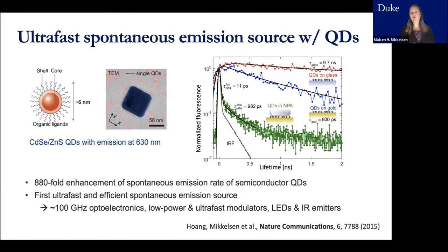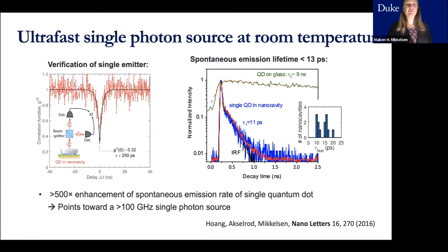This could also be very useful in enhancing II-VI emitters that can often typically be very dim. I want to point out that we're not exciting them at this point at high rates, because we start to have stability issues for the materials, that they can photobleach, but we are not limited by the electron hole recombination anymore. That is happening at a very fast rate. Later on, I will show you how fast we can actually modulate the spontaneous emission rate.